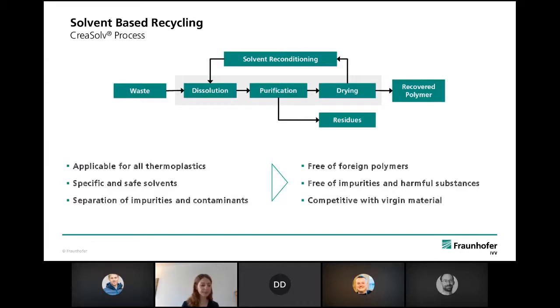So in the first step, we have a dissolution step. And for this purpose, we have different solvents and different solvent mixtures also, which selectively dissolve individual polymers. And then those dissolved polymers can be separated from the non-dissolved parts. So we have a residue and a polymer solution. The polymer can be regained from the solution, for example, by precipitation. And afterwards, we have to dry the polymer and can reprocess it. The solvent has to be distilled and be recovered so we can use it again. So we have a closed loop for the solvent.